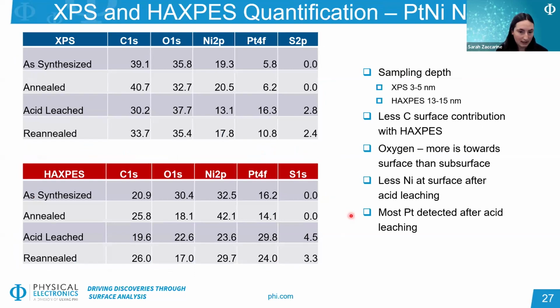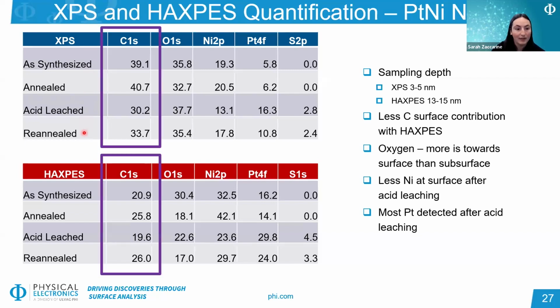And I mentioned we can also use this technique for quantification. So we were able to quantify with XPS on the top table and then HAXPES on the bottom as a function of these different processing steps. In addition to the nickel and platinum, we see some carbon present. Generally, the carbon is much lower concentration with the HAXPES source, and this is one benefit of using this deeper source, that you're seeing a little bit more into the true chemistry beneath any sort of surface contamination. We also see some differences in the carbon with post-processing steps, and we see a little bit of a trend where generally the acid-leached reannealed ones have slightly lower carbon at the surface, and especially acid-leached even in the subsurface.